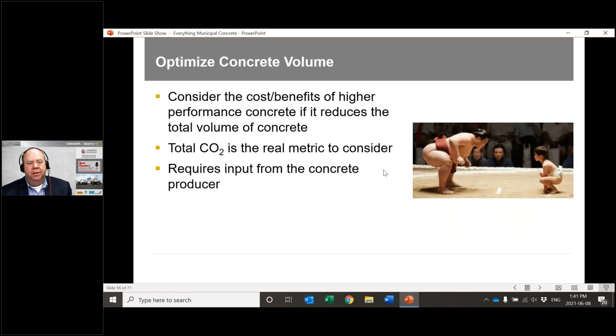Next one is looking at what's the appropriate volume and do you need that volume of concrete? So again, it can have a fairly high CO2 impact. So again, from a design standpoint, if I went with a higher strength, but a much smaller column size, could that benefit the overall structure? So as we move into an era where we start quantifying for each of our mix designs what the CO2 impacts are, then we can start looking at, from a design standpoint, how do we optimize for the right size of concrete elements out on the job site.